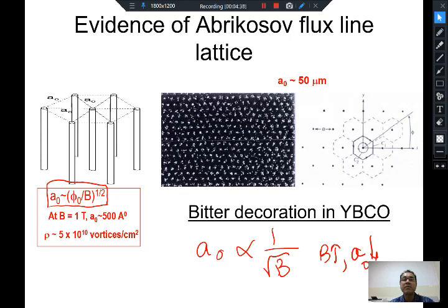And because it does not have a charge, there is no effect of the magnetic field on the neutron per se, except that the magnetic moment of the neutron is what is scattering the neutron from the vortex. Okay, so you can send in a beam of slow moving neutrons whose wavelength is large, and the scattering of this beam of slow moving neutrons will give rise to a diffraction pattern, just like you diffract x-rays from a lattice structure and you will see your diffracted intensity Bragg diffraction spots.